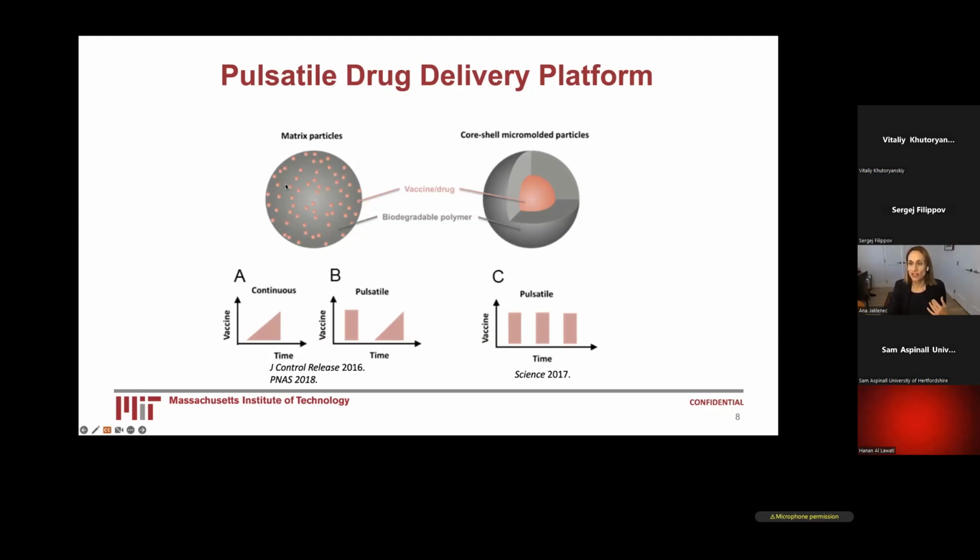make these types of formulations, when they're hydrated, that is when they're injected into the body, you'll have this instant release, which is usually shown as a pulse that releases your biologic from the surface of the particle. Then over time, the pores left behind from that initial burst allow the biologic throughout that particle to diffuse slowly. With that, you can tweak the formulation and get continuous release kinetics, or something like a pulsatile release kinetic that's maybe a little closer to what you would get with subsequent immunization shots. But in this case, you usually have a big pulse, then a quiescent period, and then this slow release later, which is governed by the diffusion and degradation of the particle.